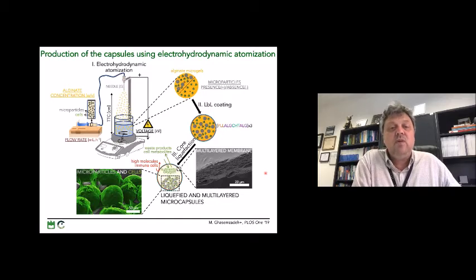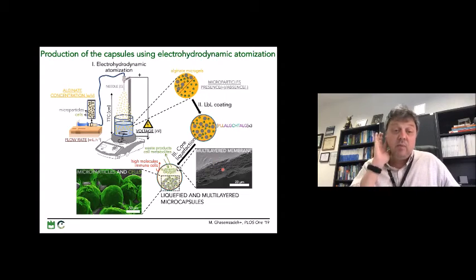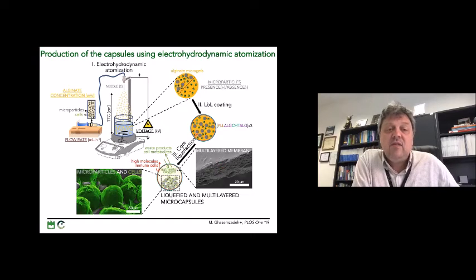And then what we do is to coat the beads using layer-by-layer technology. So we have been using alginate, chitosan, and polylysine to coat, and depending on the number of layers and the nature of the polymers, we can have a coating with different properties, and this will be very important in the end in terms of mass transport and degradation. And then finally we go for a core liquefaction. We use EDTA, that is a chelating agent for calcium, to liquefy the core. Of course, the membrane will be intact and will protect everything.